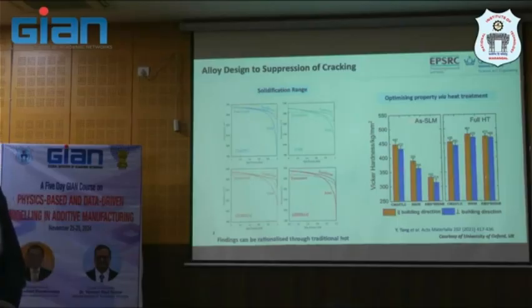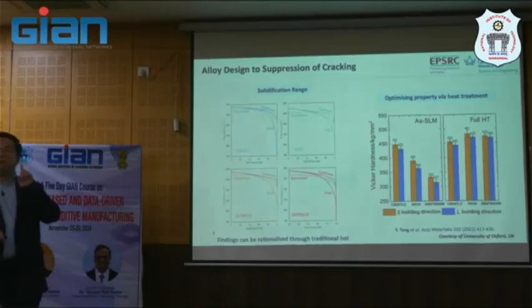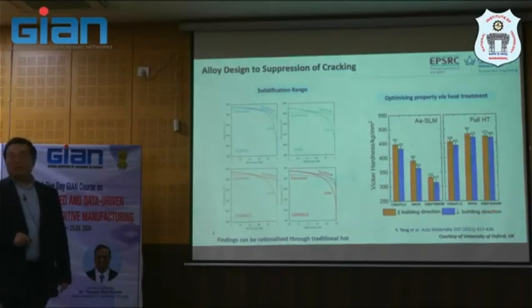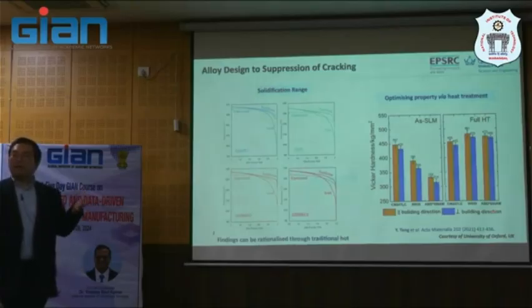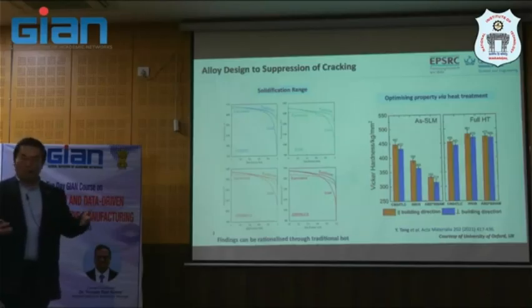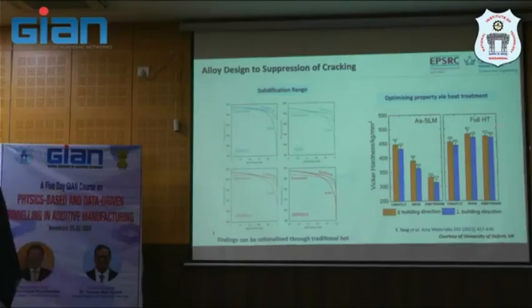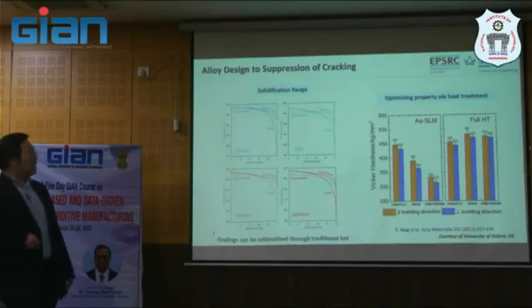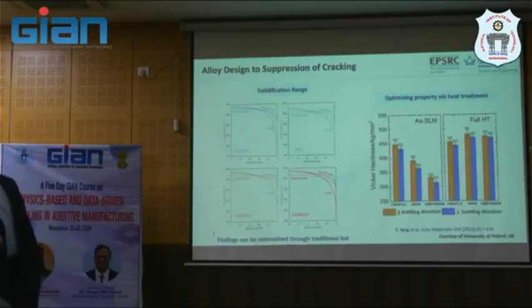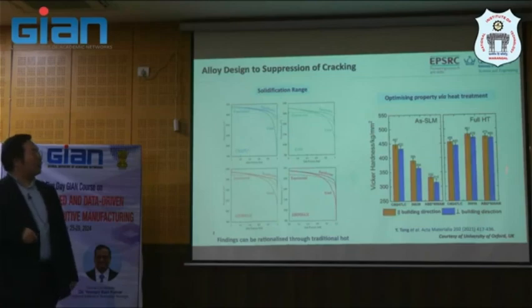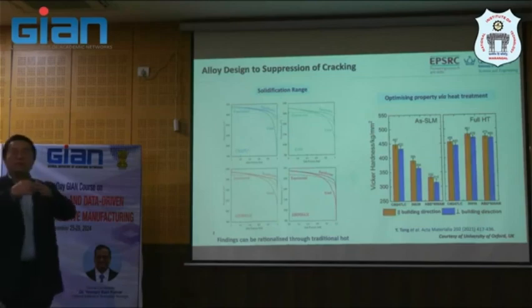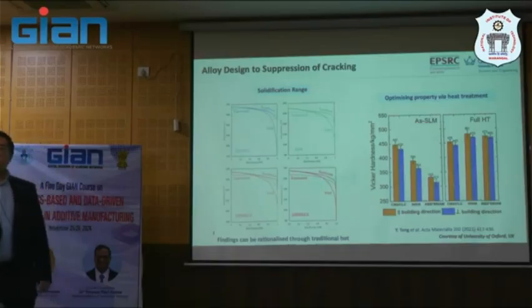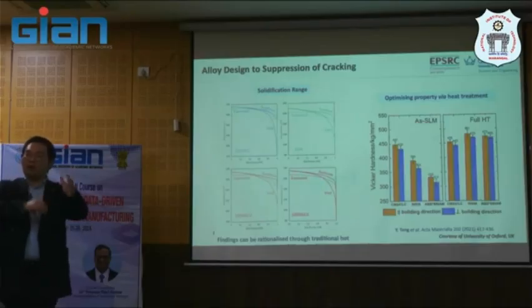So previously, if you use just hardness, it's actually quite soft during printing, especially here. But you can recover the strength back by one single heat treatment cycle, precipitating out the secondary phase. So this is probably something that we cannot just simply dream or speculate. It's happening here in this very systematic investigation, where the property along the build and transverse directions is actually quite similar. It's not very mismatched like others. You see, if it's very anisotropic, it will be quite different.